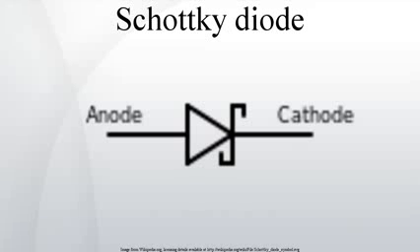Titanium silicide and other refractory silicides, which are able to withstand the temperatures needed for source drain annealing in CMOS processes, usually have too low forward voltage to be useful. Processes using these silicides therefore usually do not offer Schottky diodes.